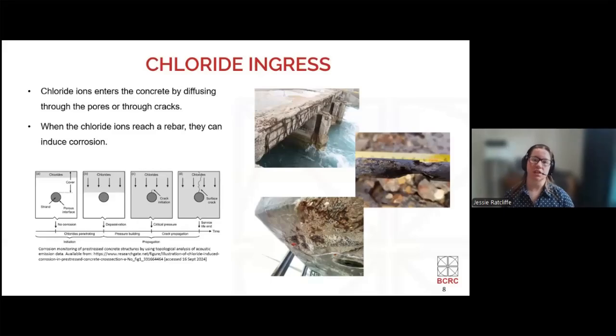We're also interested in the chloride profile of the concrete, that is the amount of chlorides present at different depths towards the reinforcement. Chloride ions enter the concrete by diffusing through the pores or through cracks, such as mechanically induced or shrinkage cracks. And then when the chloride ions reach the reinforcement, they can induce corrosion. Similar to the carbonation, they're thought to disrupt the passive film on the steel, reduce the pH level of the pore solution, and serve as a catalyst for oxidation of the reinforcement.